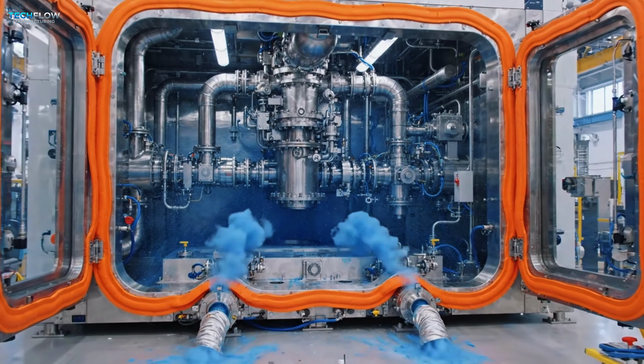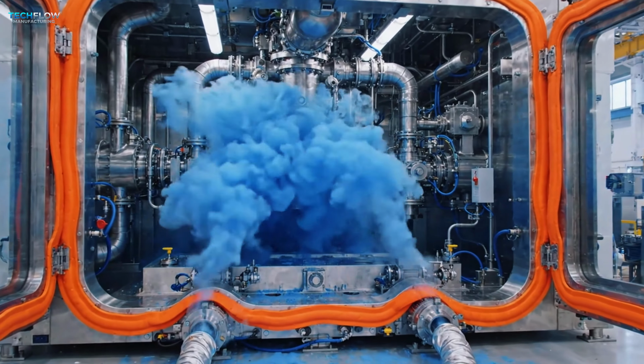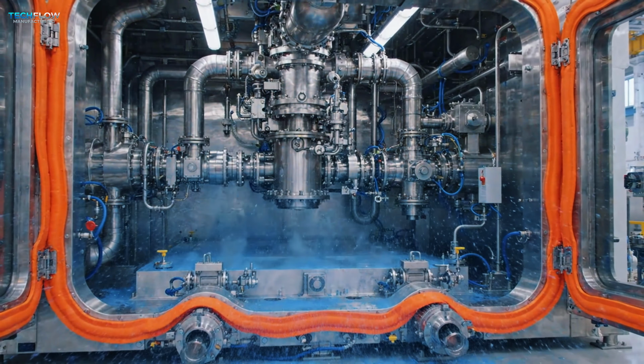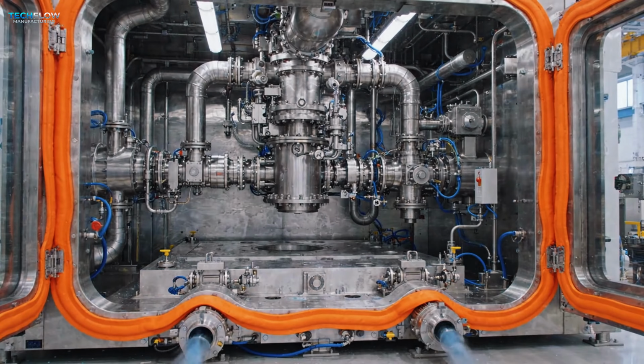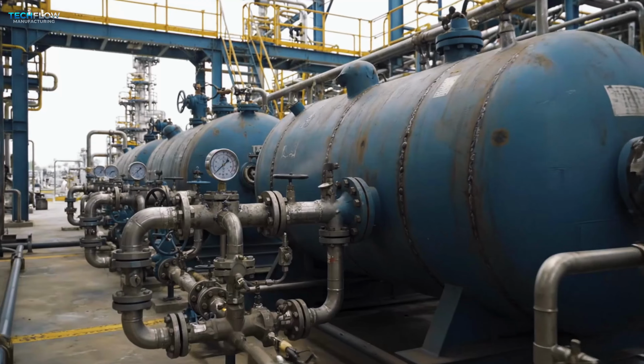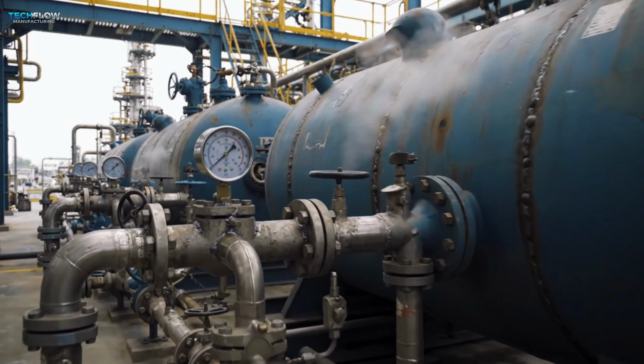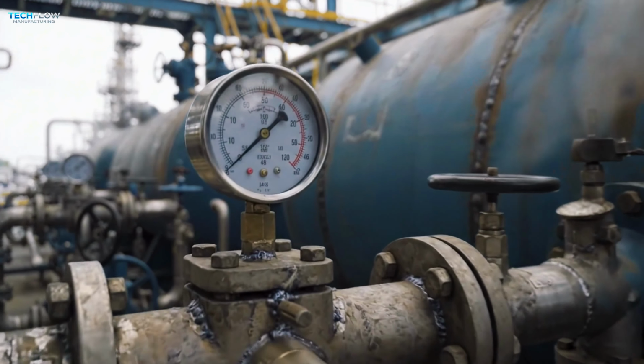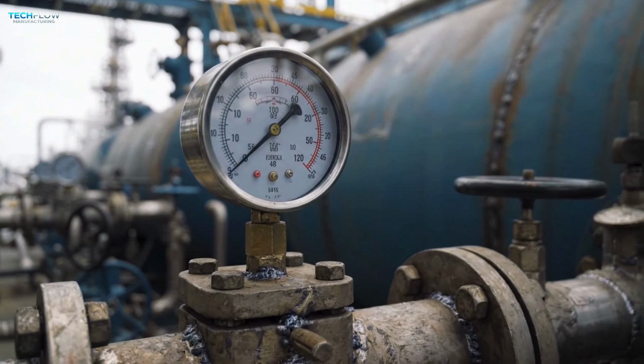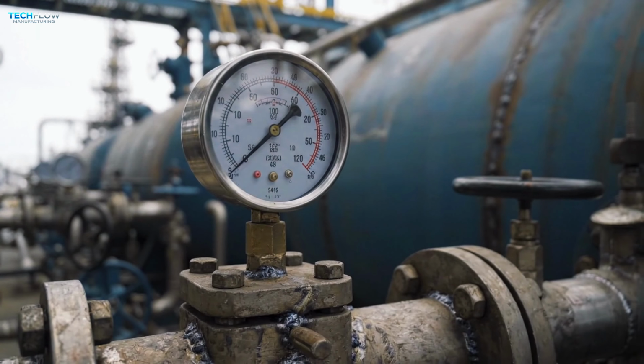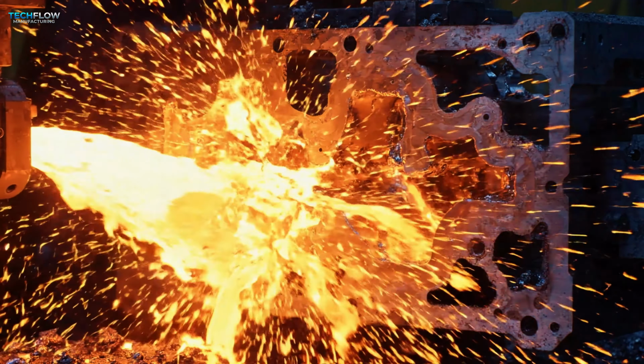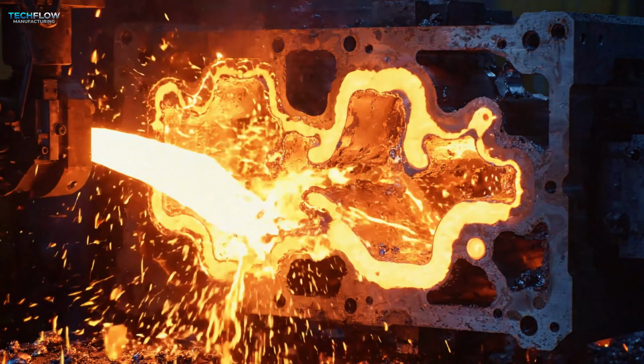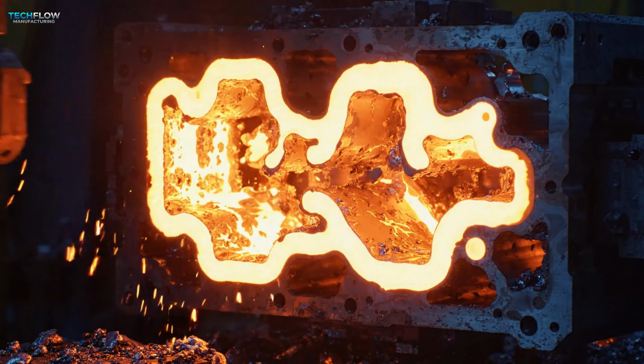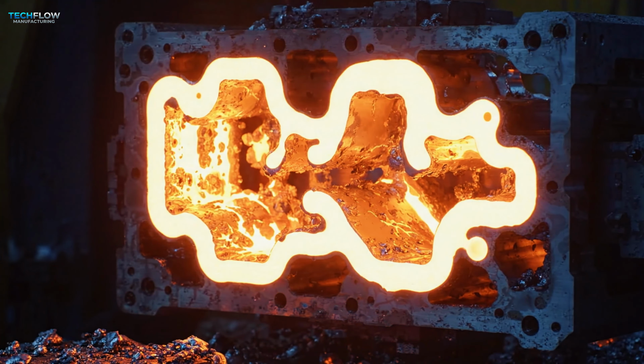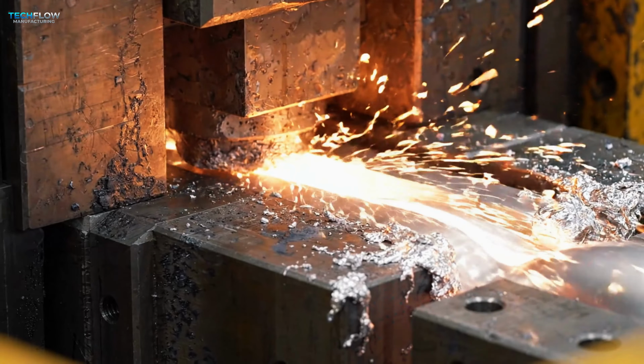minutes. The injection process happens in a vacuum. Any trapped air would create microscopic voids, weakening the entire rear assembly. As the shot sleeve fills, a massive plunger accelerates, forced by nitrogen-powered accumulators for maximum kinetic energy. The metal travels through the runner system at speeds exceeding 50 meters per second, filling the die before it can solidify. Observe the complexity of the gate design.